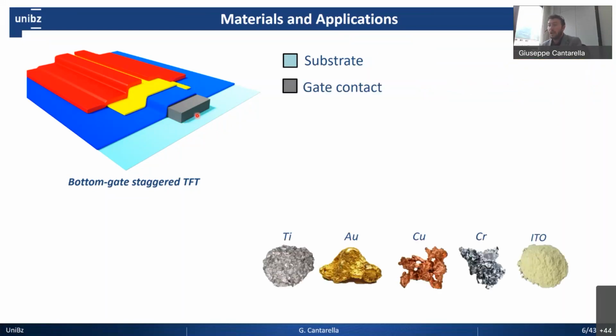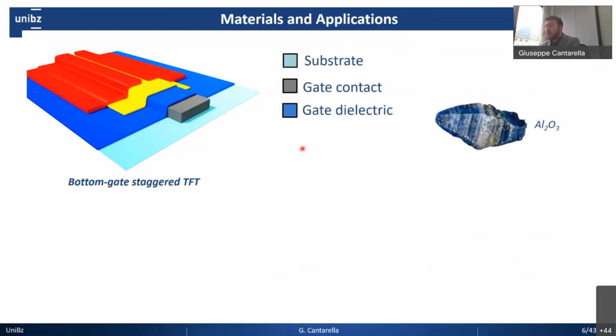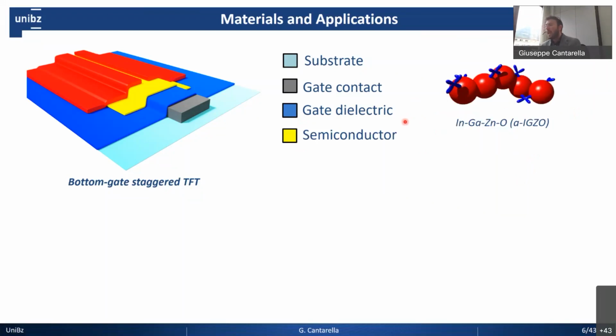Then comes the deposition and structuring of the gate metal. Usually we had the possibility to apply, through vacuum-based processings, a lot of different materials according to the application. So from titanium, gold, chromium, copper, up to something more fancy, such as indium tin oxide in case, for example, of transparent application. Then afterwards, the dielectric. So we need to make sure to employ an insulator layer, which is very conformable and pinhole free. That's why we use aluminum oxide deposited by atomic layer deposition. The deposition of this layer is the highest deposition temperature that we employ in our fabrication, which is 150 degrees. And then comes the semiconductor.